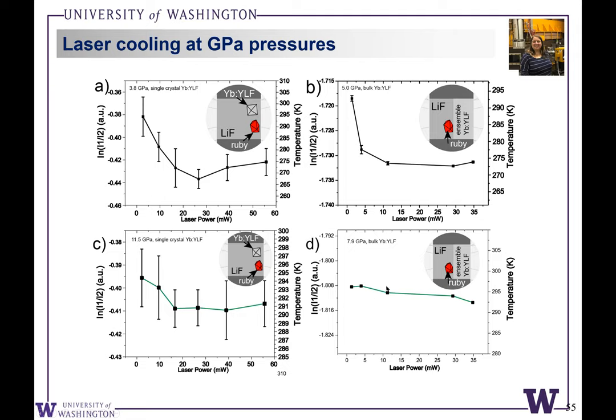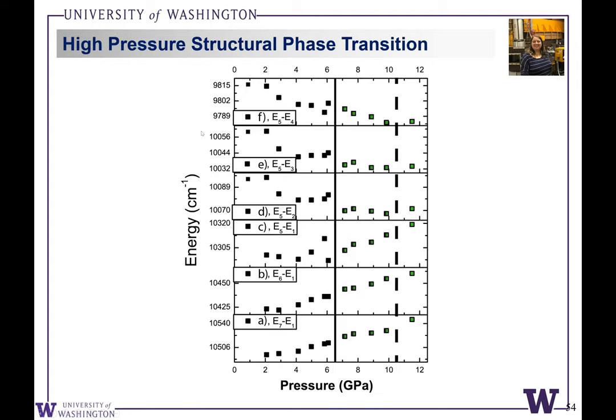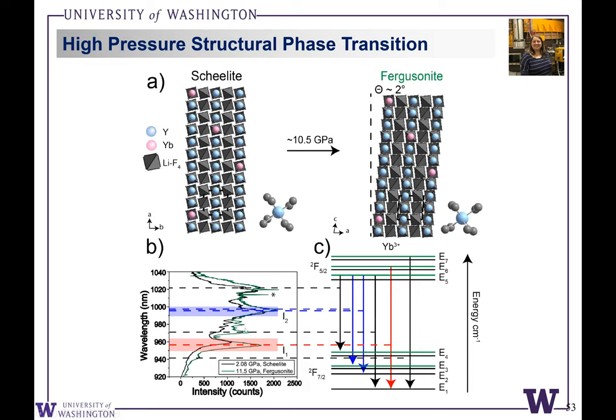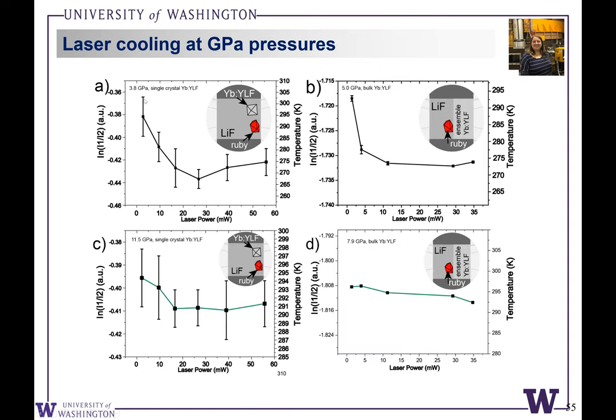We've actually posted this manuscript to the archive too. I apologize, I forgot to include that link in this talk, but these are the data just showing the lanthanide emission. We look at the crystal field emission and we integrate the blue spectral regions and take a ratio with the red spectral regions, and we can fit that to a Boltzmann distribution. We can also calibrate that with a thermoelectrically cooled DAC. And we can calibrate that temperature as a function of crystal field splitting and also the Boltzmann ratio method.